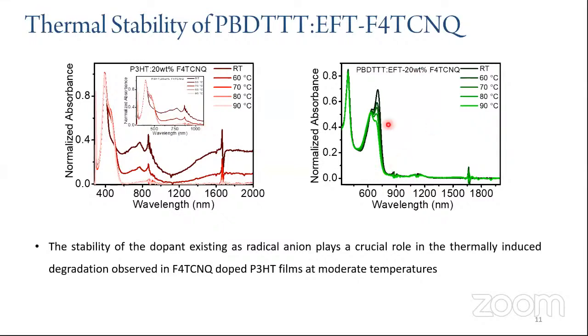In our proposed system, we can see that at a moderate range from 60 degree to 90 degree, the de-doping does not occur, or it is not visible from the optical signatures. So the stability of the dopant that is existing as a radical anion in the system is playing a crucial role in thermally induced degradation observed in F4TCNQ doped P3HT films at even moderate temperatures.